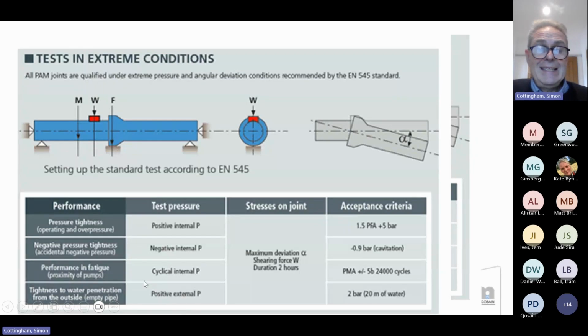The joint is given a very rigorous test. So in terms of its positive internal pressure, the pipe is tested to 1.5 times working pressure plus 5 bar. So where our minimum pressure rating is a class 20 bar pipe, we will test it to 30 bar plus 5, so a 35 bar test. So it gives a very rigorous internal pressure capability. In terms of negative pressure, we can go to minus 0.9 bar negative pressure.